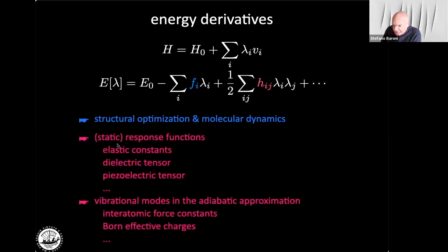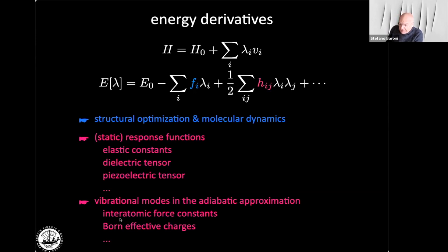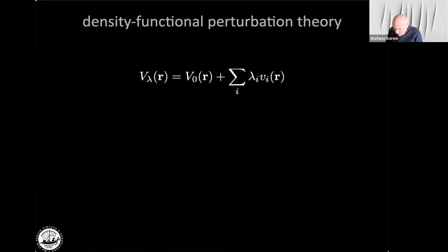Second derivatives give access to static response functions such as elastic constants, dielectric tensors, and piezoelectric tensors. Extending this to microscopic quantities like interatomic force constants and Born effective charges allows us to compute vibrational frequencies of molecules and solids.